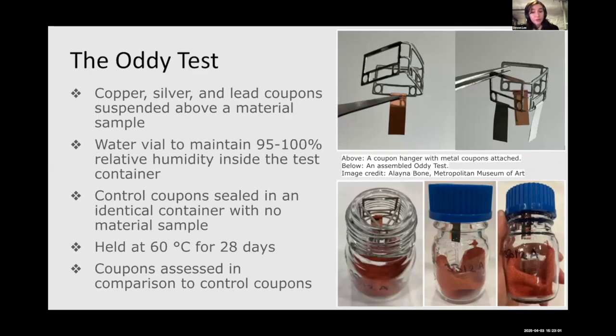How the test works generally is that a small sample of the material, say a gasket or a fabric, like in the image, is placed in a sealable container. Three metal coupons, one each of copper, silver, and lead, are exposed to the headspace above the material sample. The image on the slide here is an example of an Oddy test assembly. The material sample is sealed in a container beneath the suspended metal coupons alongside an open vial of water, which brings the interior of the assembly to about 95 to 100% relative humidity, while the assembly is held at 60 degrees Celsius for 28 days.